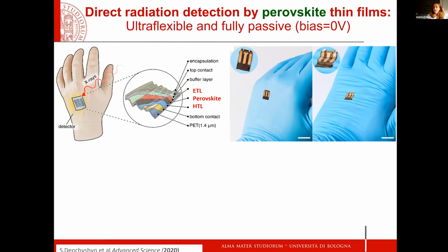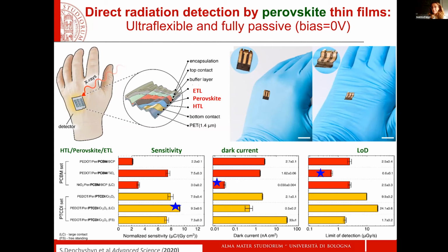Why did we do that? Because we wanted to see the effect of the interface in the radiation collection in such a thin structure. And the output was really interesting, because you see that even if we have the exactly identical perovskite thickness and material, by changing the interfaces of the electron and hole collecting layers, we really change enormously the 3 major figures of merit for high energy radiation detectors. Of course, I'm talking about the sensitivity, the dark current, and the LOD, which is the limit of detection.